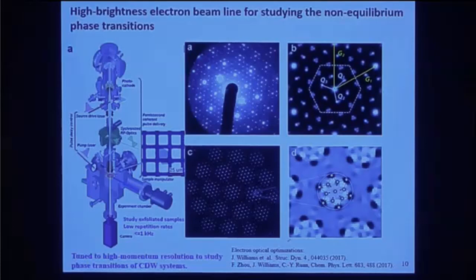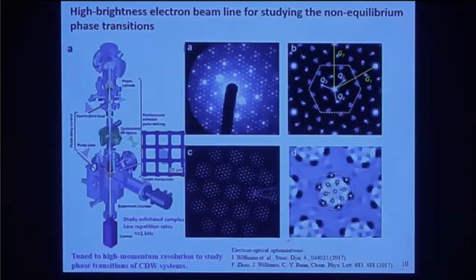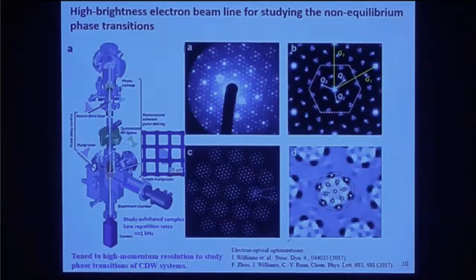Usually in electron microscopy you measure real space, not momentum space. With an electron microscope, you can operate in both imaging mode and diffraction mode. Even the best electron microscope has a resolution of about 0.3–0.5 Ångstroms, but the inter-atomic vibration from density wave distortion is on the order of 0.001 Ångstroms. So you do diffraction, which gives you higher spatial resolution because in the Fourier transform, your momentum space is very large and you can get very fine scale information.